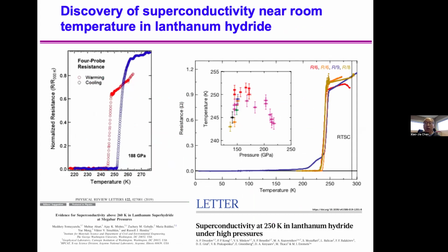It's a PRL paper. For that paper, there was also work from Michael Eremets. You can see the Tc from resistivity measurements showing at around 200 GPa. The Tc drops and reaches the zero resistance state above 260 Kelvin in both measurements. Now, room temperature superconductivity comes. That's from the rare earth element hydrides. This is a real case.